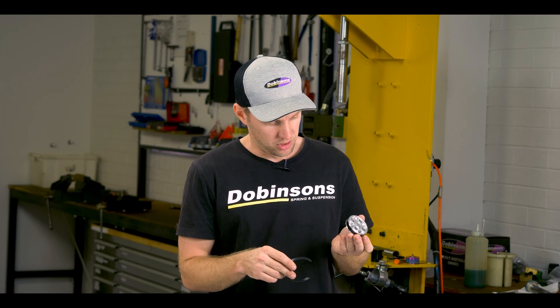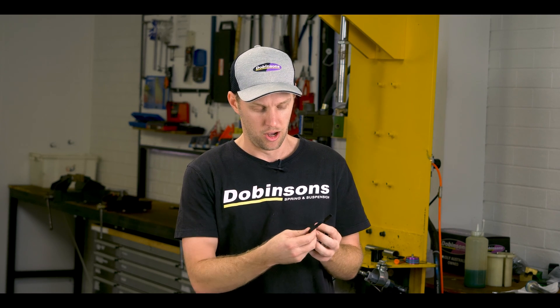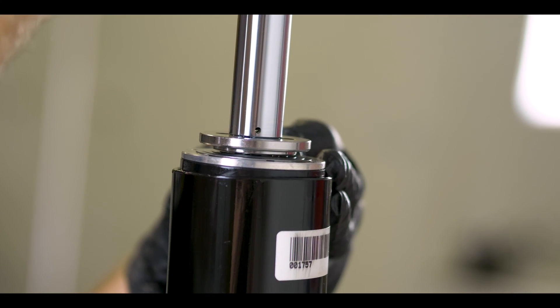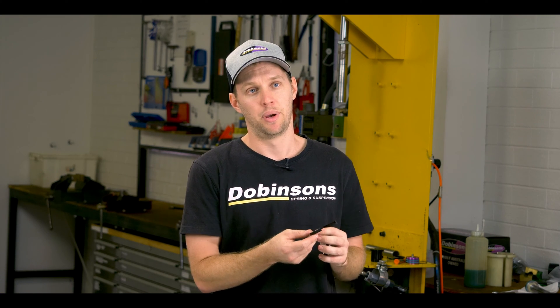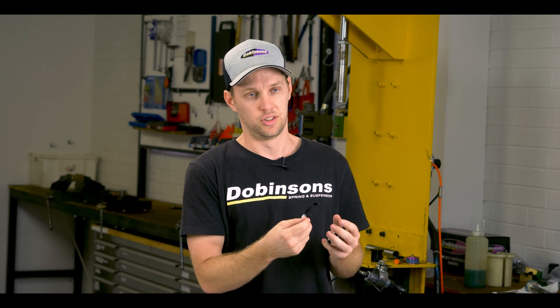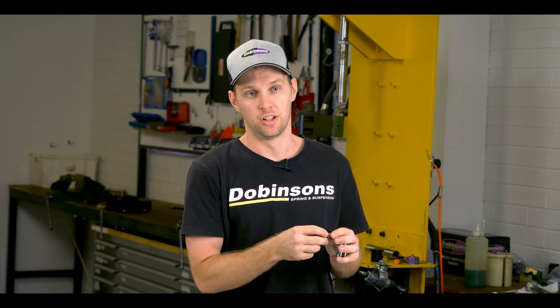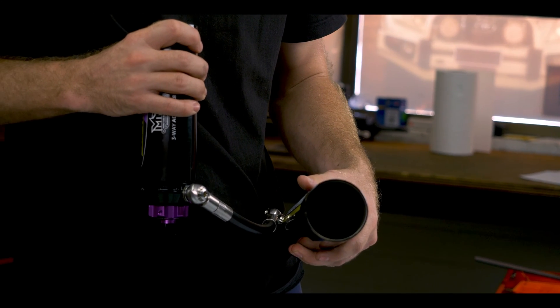Looking at the wear band itself, we run a composite wear band rather than just a single material. We want to have a good seal but also keep friction to a minimum. We ended up settling on a PTFE, carbon fibre, molybdenum disulfide composite wear band, which in our testing gave us the lowest possible drag and friction while also providing a good seal against the inner surface of our main working bodies.